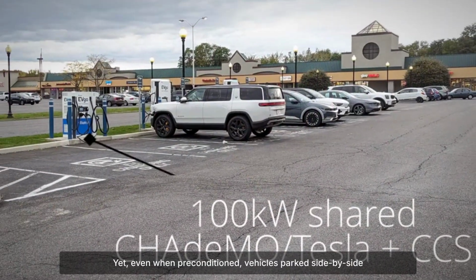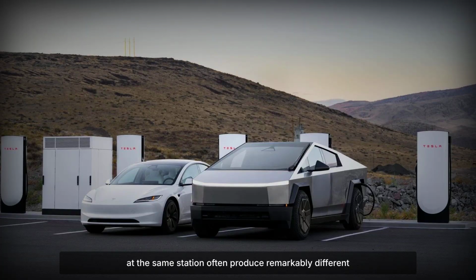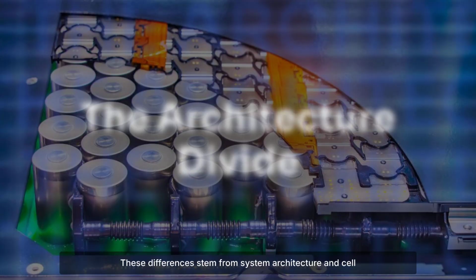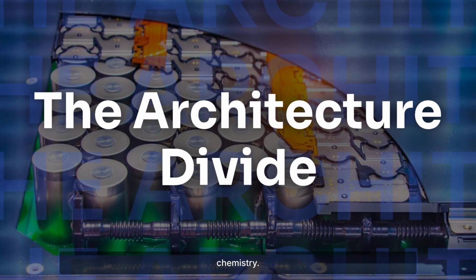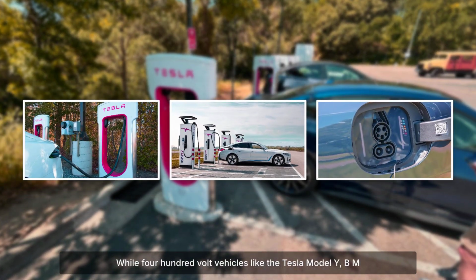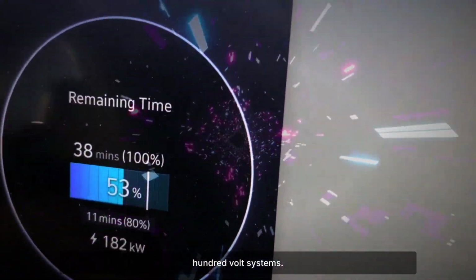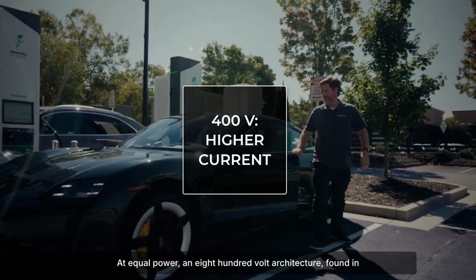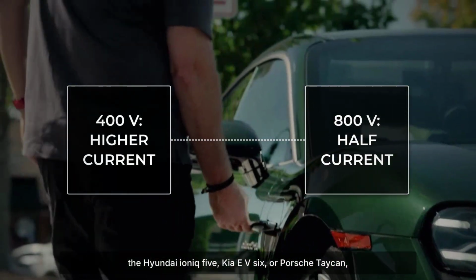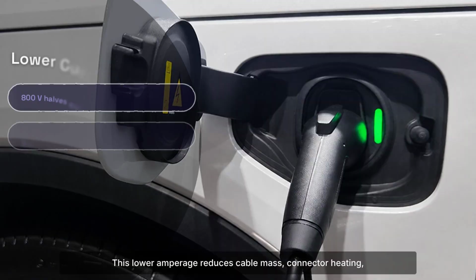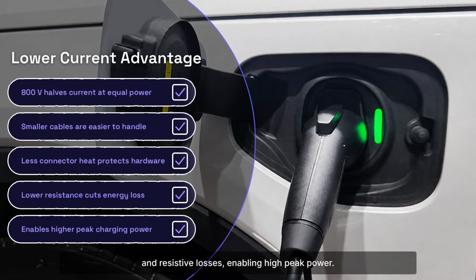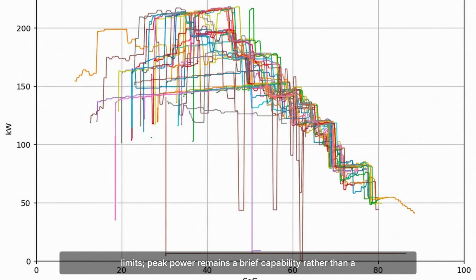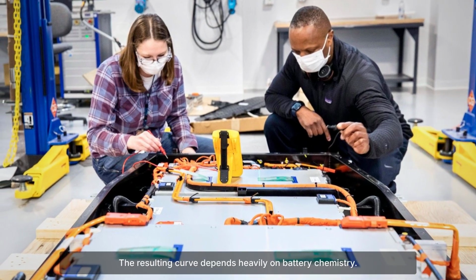Yet, even when preconditioned, vehicles parked side by side at the same station often produce remarkably different charging curves. These differences stem from system architecture and cell chemistry. While 400-volt vehicles like the Tesla Model Y, BMW i4, and Mercedes EQE dominate, others adopt 800-volt systems. At equal power, an 800-volt architecture found in the Hyundai Ioniq 5, Kia EV6, or Porsche Taycan halves the current. This lower amperage reduces cable mass, connector heating, and resistive losses, enabling high peak power. Yet 800-volt cannot bypass fundamental cell limits. Peak power remains a brief capability rather than a session-long rate. The resulting curve depends heavily on battery chemistry.